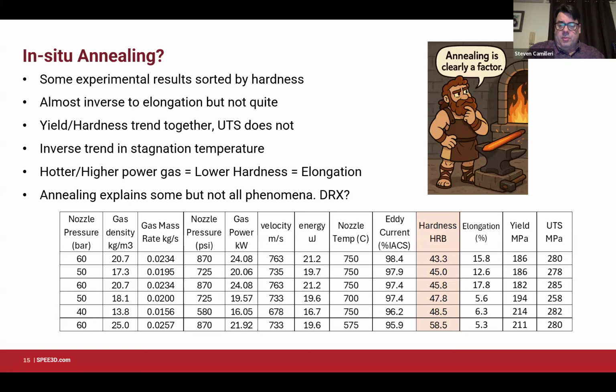There's quite a big range there, 50% in hardness as we go from the hot, high temperature, high pressure gas down to the cooler gas. There's quite a big difference there. And indeed, those hardnesses correlate with the yields, which would suggest an annealing type behavior. But interestingly, the UTS doesn't substantially change. So if anyone's got a theory about why that happens, let me know. We haven't been able to work that one out, but it's a fascinating result all the same.